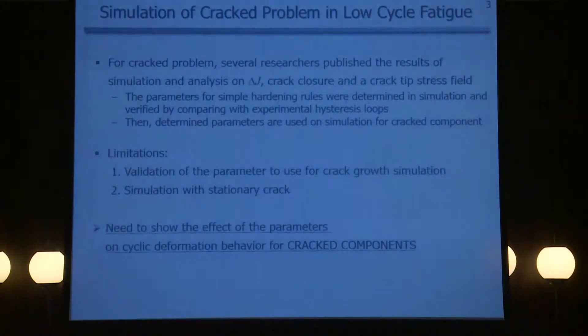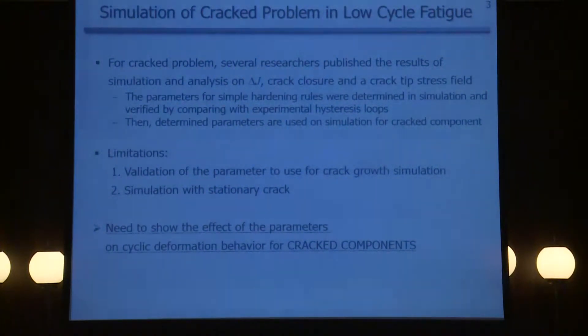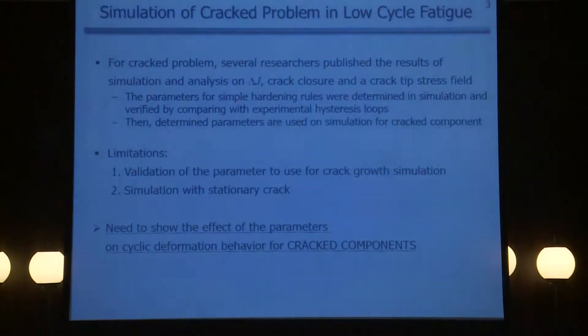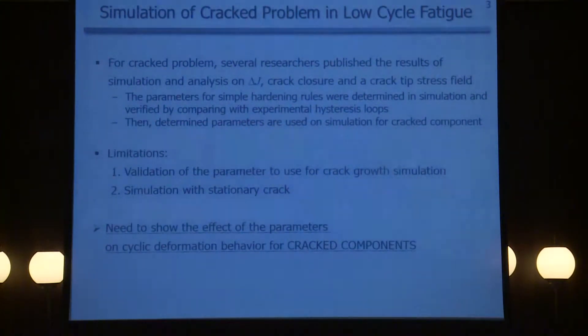We want to apply this cyclic hardening model to the crack problem. For the crack problem, several researchers published results on delta J, crack closure, and crack tip stress fields using simple hardening models or parameters determined from simple experimental hysteresis loops. However, those studies have limitations — they do not validate the parameters for use in crack problems before applying them to stationary crack simulation. We therefore need to show the effect of parameters on the cyclic deformation behavior for the crack component.